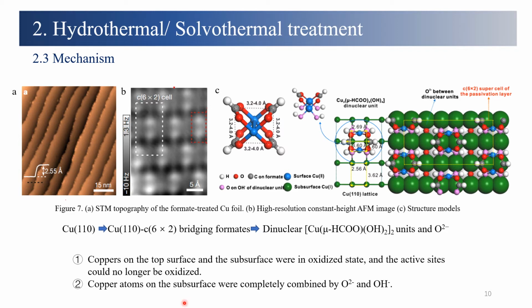Next, to figure out the detailed structure of the copper 110 surface, high-resolution images show the perfect copper 110 6+2 superlattice. Further, the authors created a 6+2 superlattice of copper 110 with a 5-layer slab to detect which coordination way copper and formate chose. A dinuclear unit, with an oxygen ion, covered the surface, which was a novel modified structure. This structure can be regarded as copper valence decreasing from surface +2 to subsurface +1 and then bulk atoms.